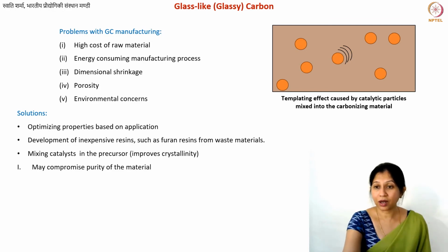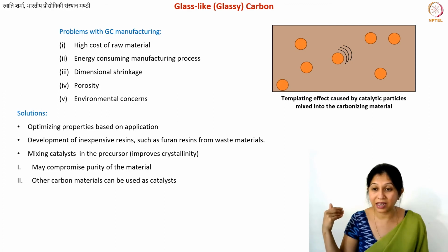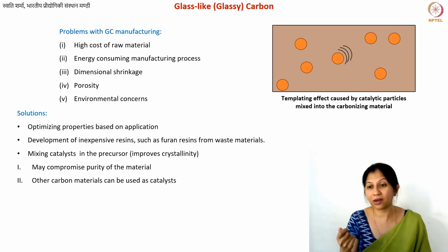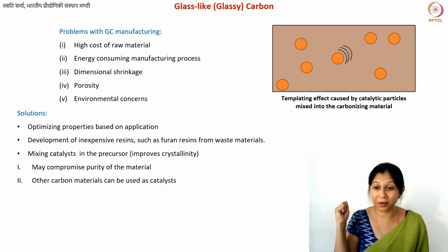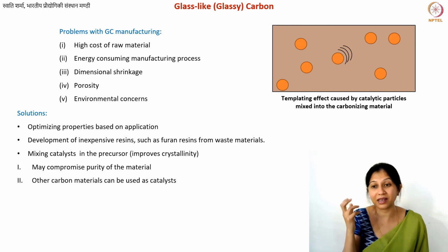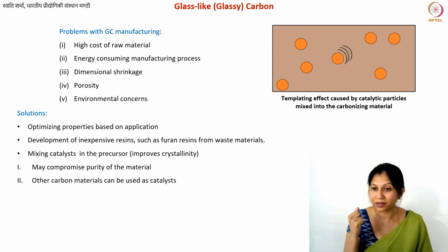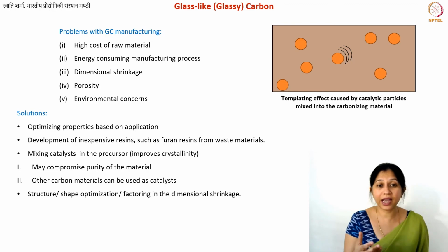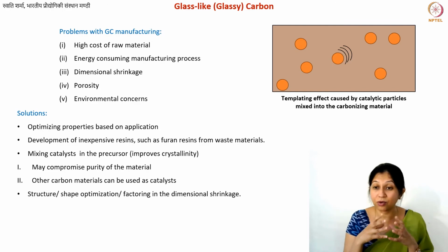Now, however, when you use any catalytic particles, you of course end up compromising the purity of your material, because afterwards you have to leach out all the particles that you added. If you have an application where it's okay to have some particles, or if you're using carbon nanomaterials as the catalytic particles, in that case you don't need to worry about it. So this is something that you need to see, whether or not using a catalyst, and which kind of catalyst, is acceptable for your material. But this is one of the solutions which can lower the overall energy consumption of the process.